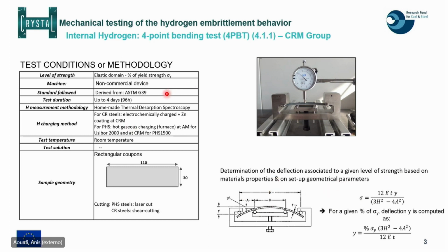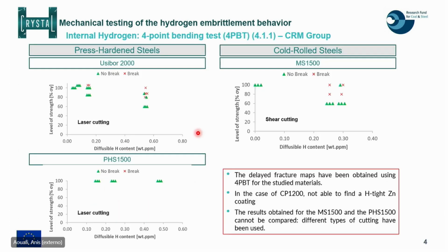So this test has been applied during 4 days on the press hardening steel and cold rolled steel with different internal hydrogen content. And the results are summed up in this slide. For press hardening steel, where the specimens are laser cut, we could obtain for all materials such a delayed fracture map with the applied stress versus diffusible hydrogen, and when the crack occurs, it's highlighted by a red point.